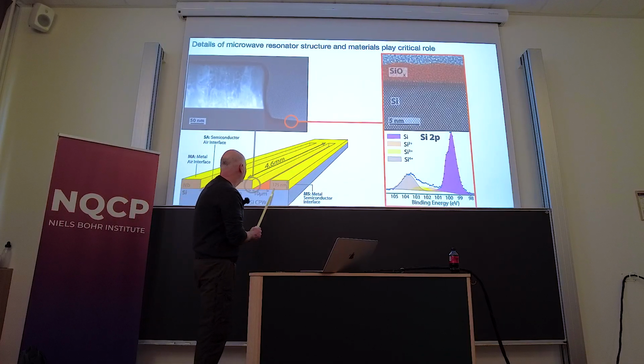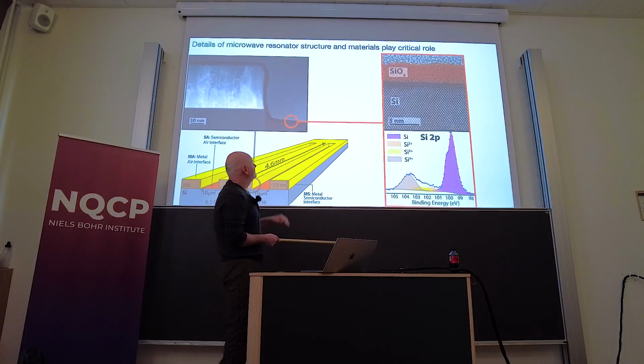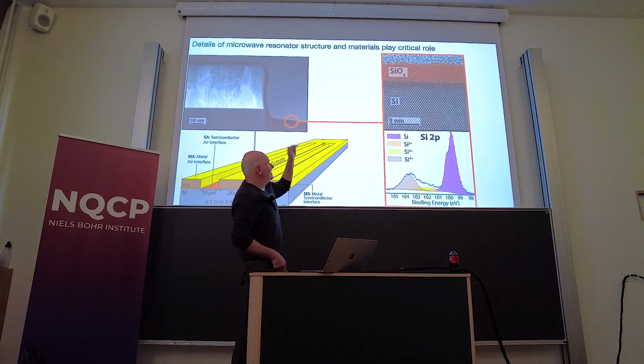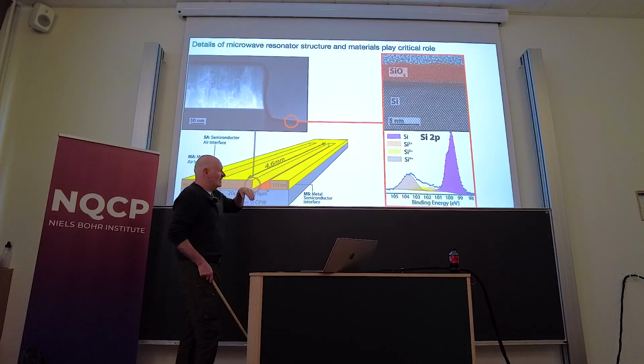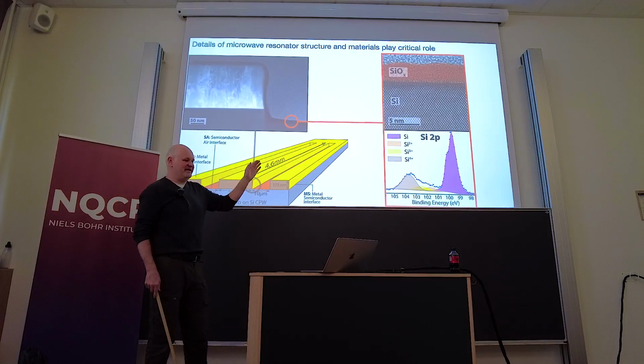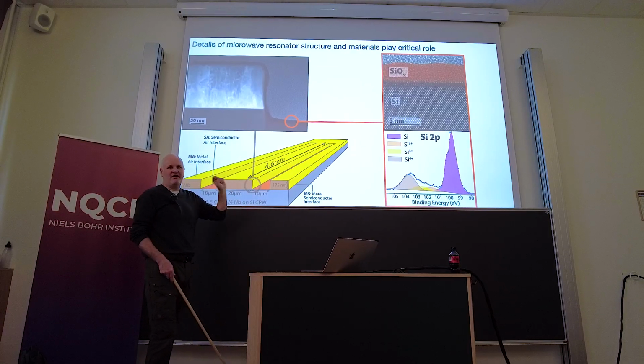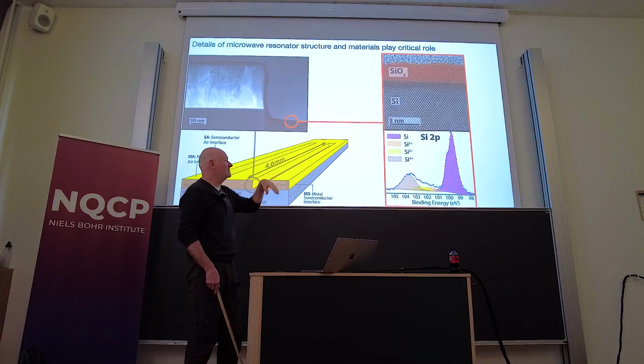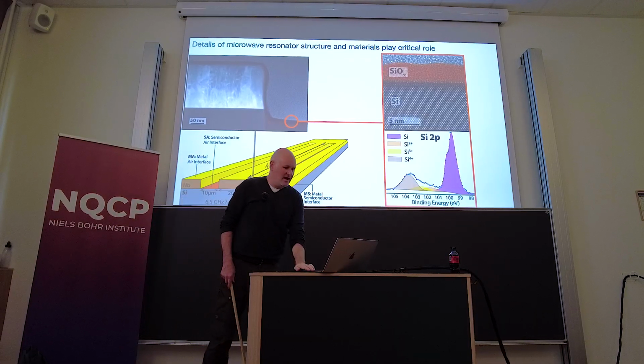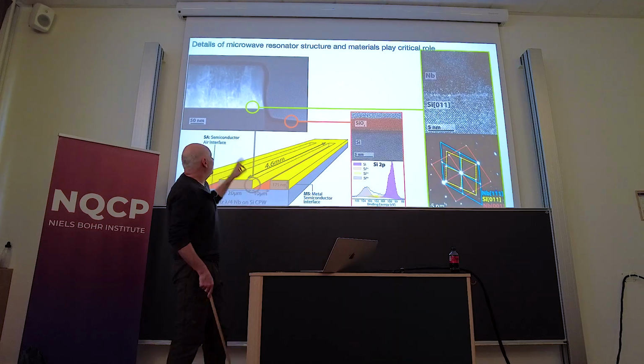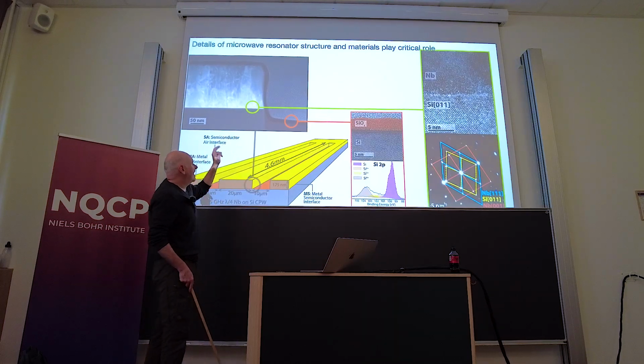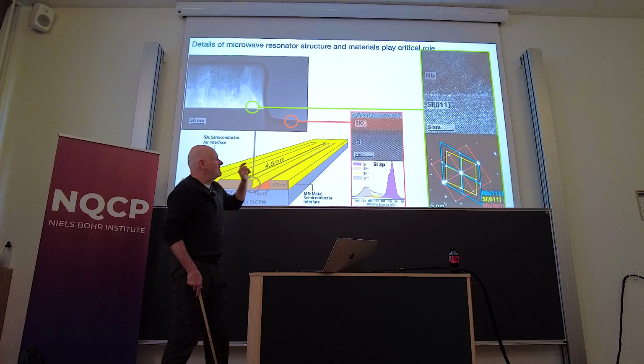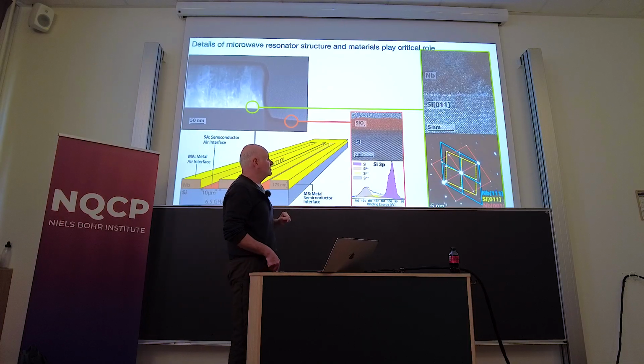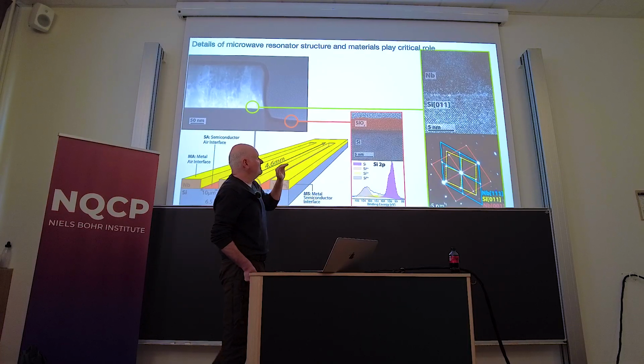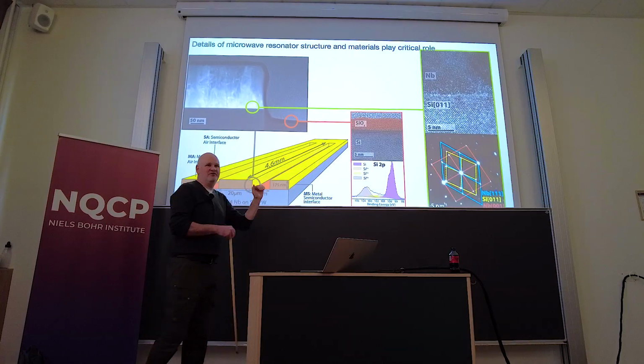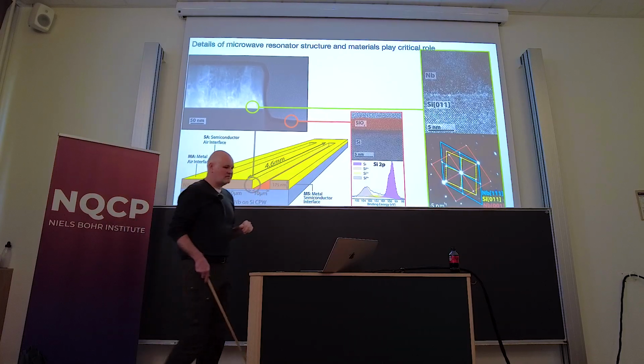So at the silicon interface, not under the niobium, you have silicon and silicon oxide, and you have a mix of silicon states. It's not just pure crystalline silicon oxide. It's amorphous, and it's kind of just a mess. You can also look at the interface between the niobium and the silicon, and there you have a better interface, but there's still some oxygen. But you do, in most places, have epitaxial growth if you do it right off of the silicon.